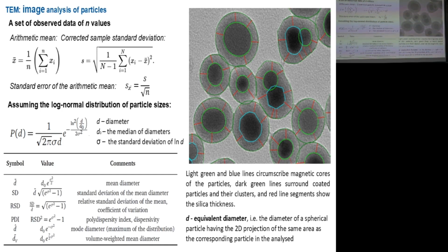Of course, you should somehow show the distribution. So you will probably calculate the standard deviation or the corrected sample standard deviation. But you have to distinguish this from the standard error or standard deviation of the arithmetic mean. This is very important. This is somehow related to the confidence interval around the arithmetic mean, whereas this quantity, this parameter describes the distribution.